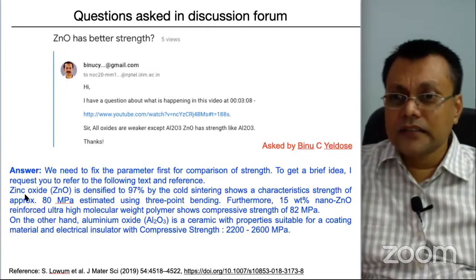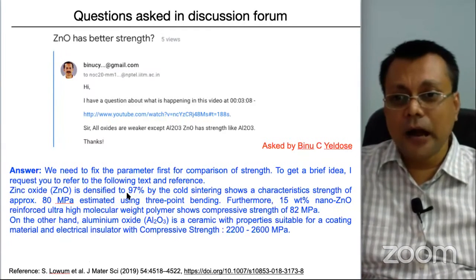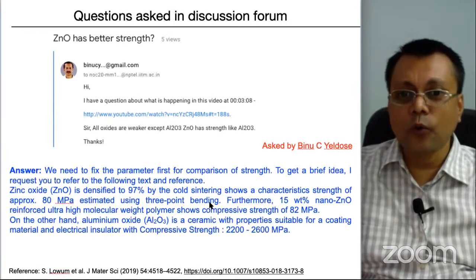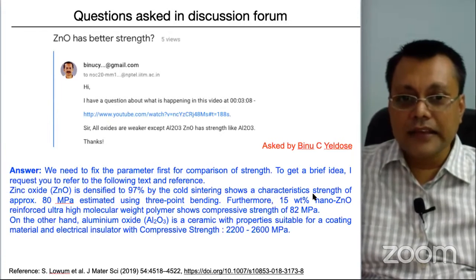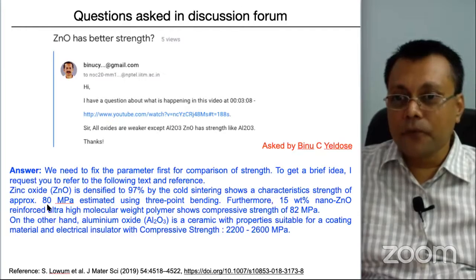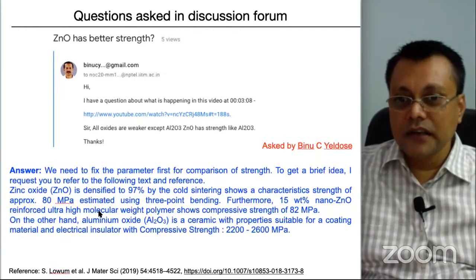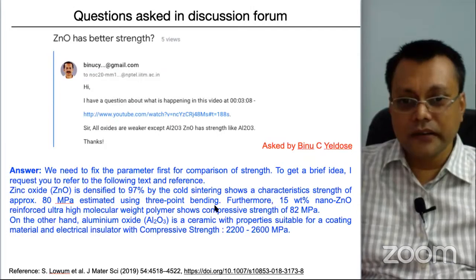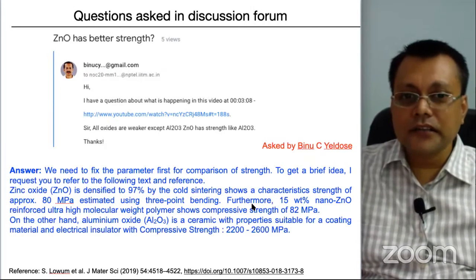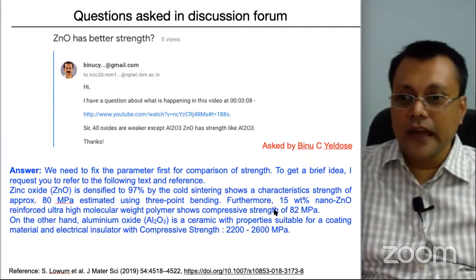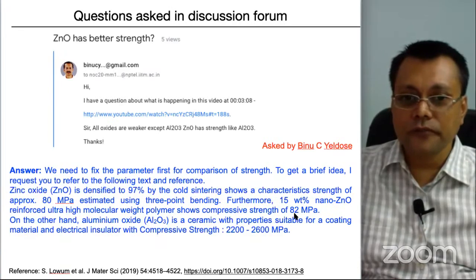Now here, the zinc oxide densified up to 97% by cold sintering shows a strength of approximately 80 megapascal, estimated by 3-point bending. However, Furthermore, 15 wt% nano zinc oxide reinforced with ultra high molecular weight polymer shows a compressive strength of 82 megapascal.